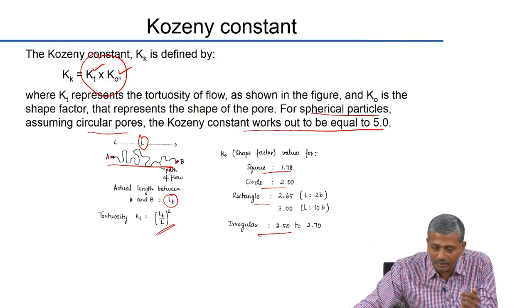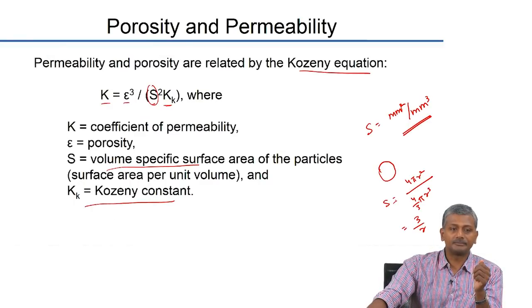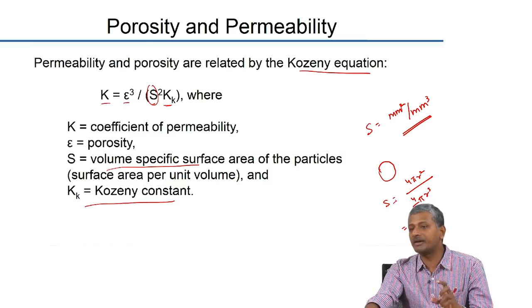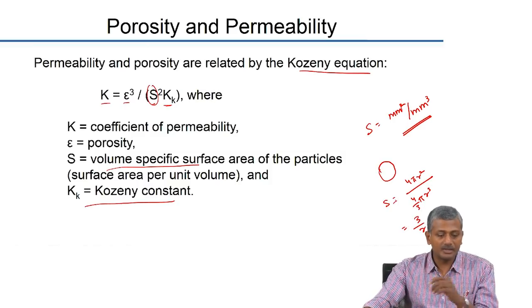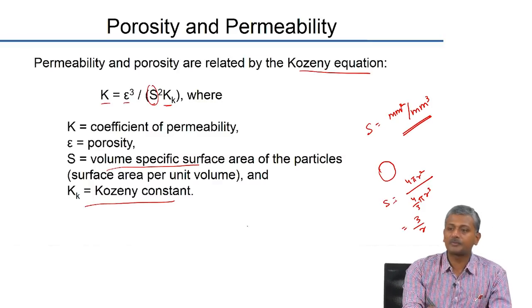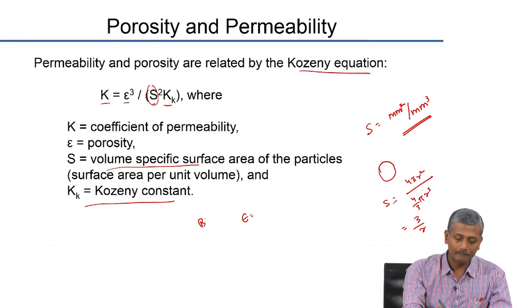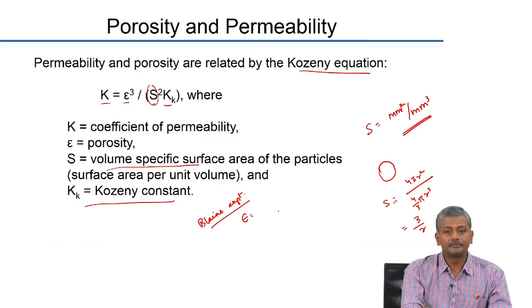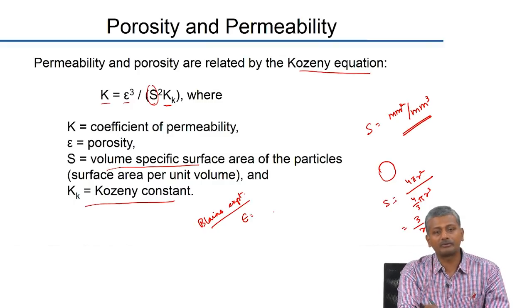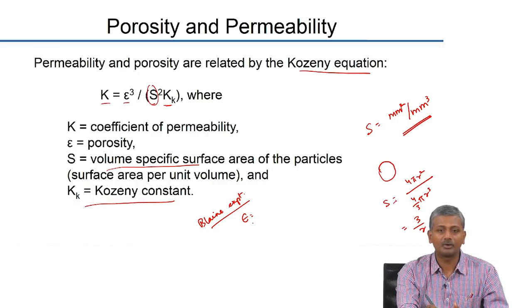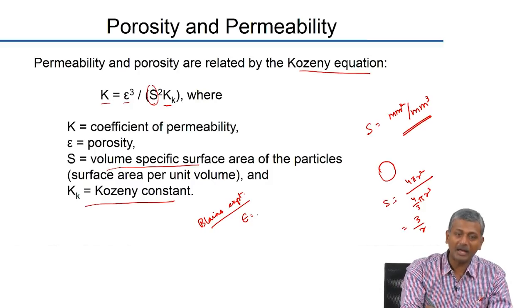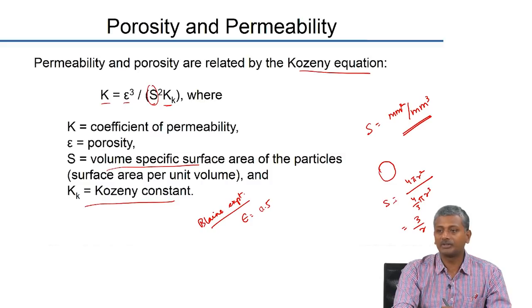Let us just do this for the Blaine air permeability experiment, where you are measuring the fineness of your cement, right? Okay. So let's do it there. So in the Blaine experiment, what is the porosity? You prepare your bed to a certain porosity. Now, how much is that porosity? You have done the Blaine experiment in class, in your lab. Nobody is sure. You did not do the Blaine air permeability experiment in the lab? Okay. The porosity that you pack the bed to is 0.5. Okay. The porosity is 0.5.